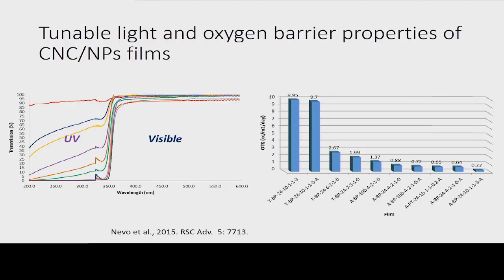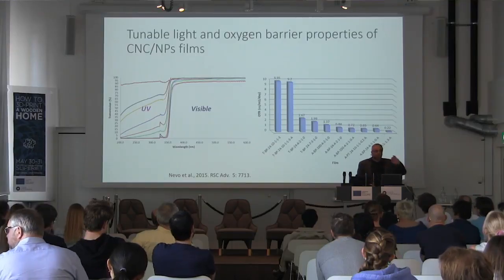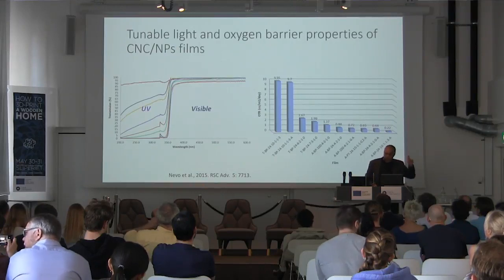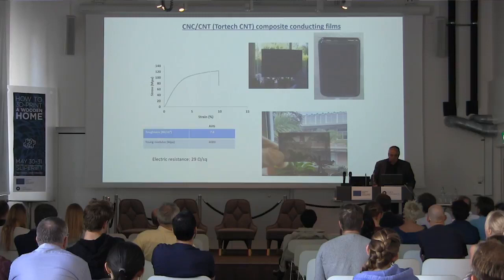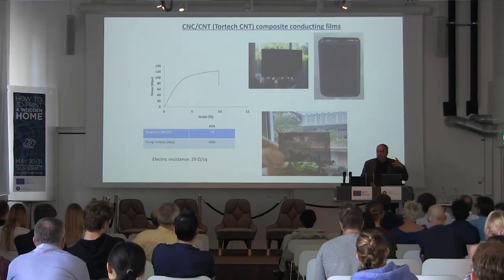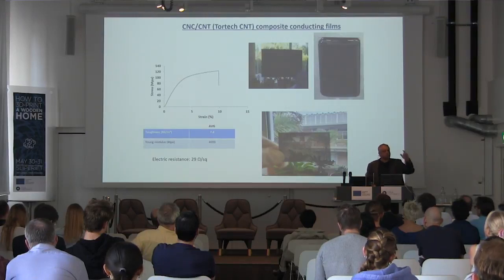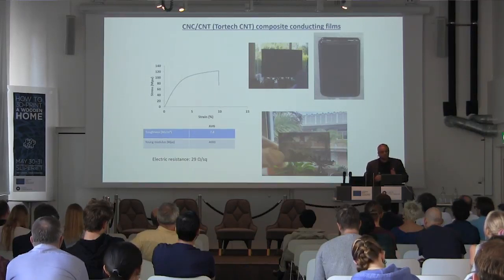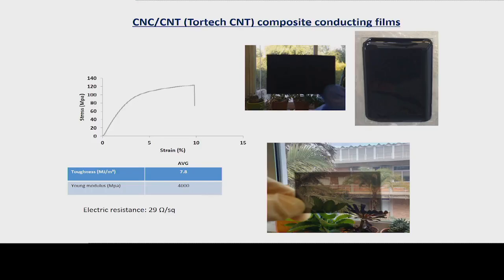So one thing that we have shown, for example, on the left-hand side, that when we add zinc oxide nanoparticles, we can effectively block the UV spectrum and leave only the visible range wide open. So that's very useful for packaging, for example, to protect materials from UV. But in addition, as you can see, nanocellulose in different formulations can be very, very effective oxygen barriers. That's another thing which is very useful for packaging. Nanocellulose can suspend things that are very difficult to suspend, like carbon nanotubes, for example. So all you have to do is take the nanocellulose, add it into carbon nanotubes, raise the temperature or sonicate, and all of a sudden carbon nanotubes are well suspended, and then you can make really either opaque or semi-transparent films, which have even some conductivity. So they can be very useful for other applications.